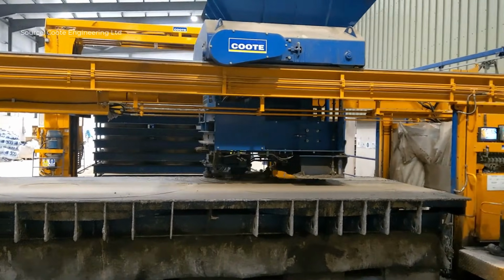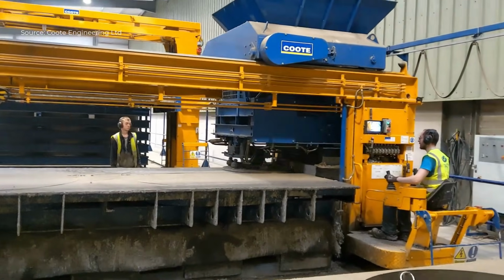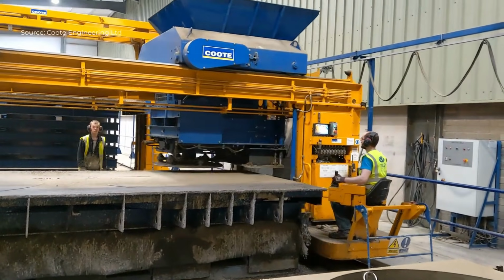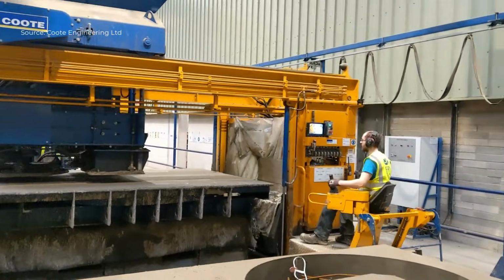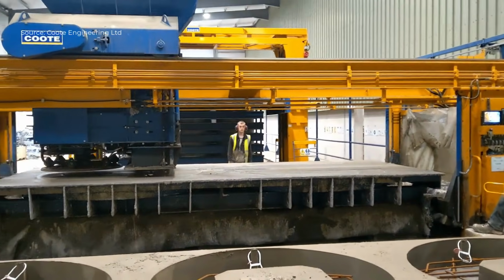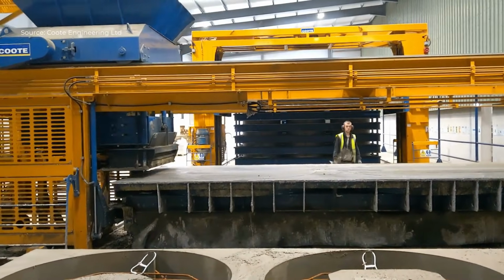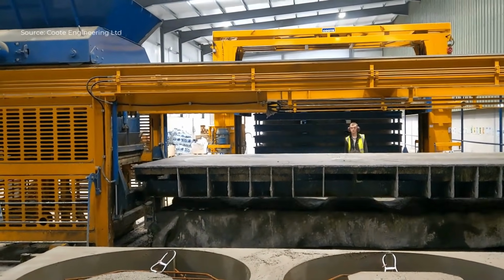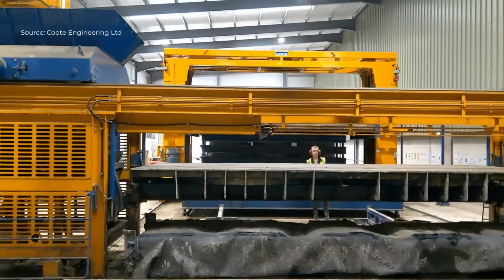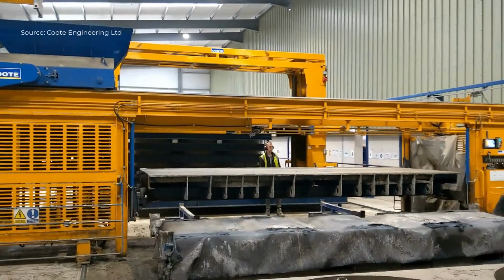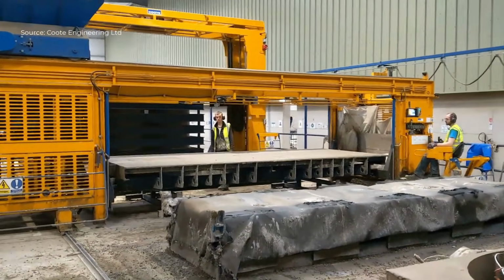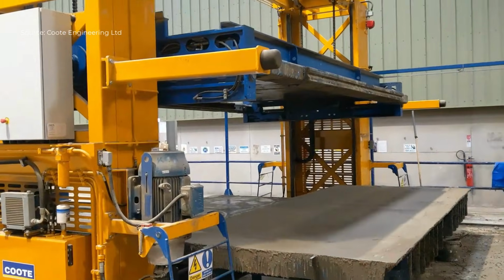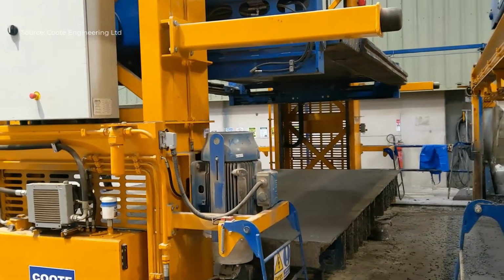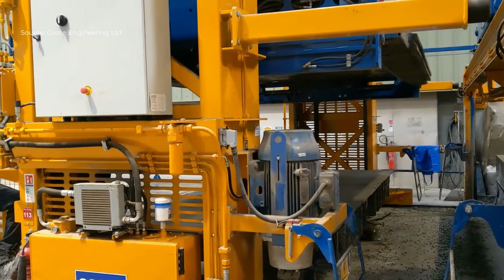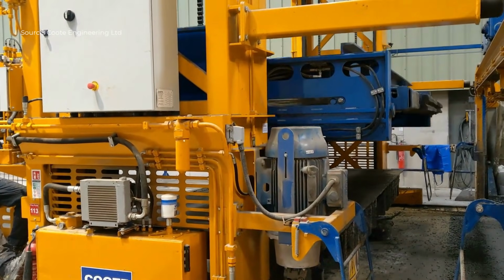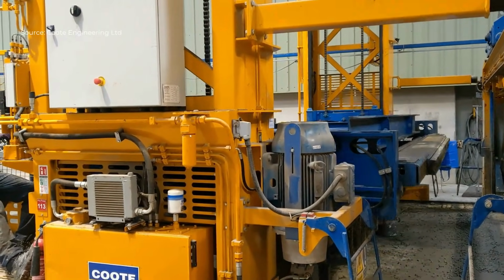Concrete is discharged onto the pallet and distributed evenly into the mold that defines the large diameter cover slab used for manhole rings. The Coote Rotoscreed mixer ensures uniform material distribution and consistent mix quality before compaction. Once the mold is filled, the pallet moves onto the Coote vibrating table. Here, powerful and precisely controlled vibration compacts the dry concrete, forcing it tightly into every detail of the mold. This vibration process eliminates air voids, increases density, and produces a smooth, high-quality surface finish despite the low water content.